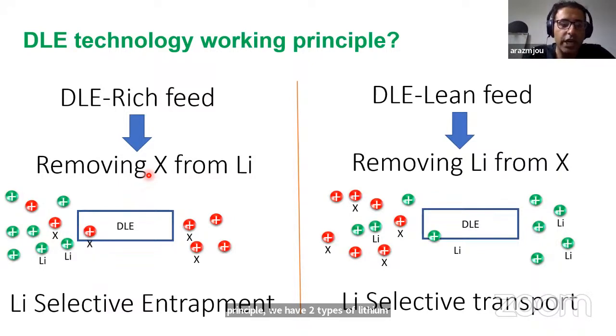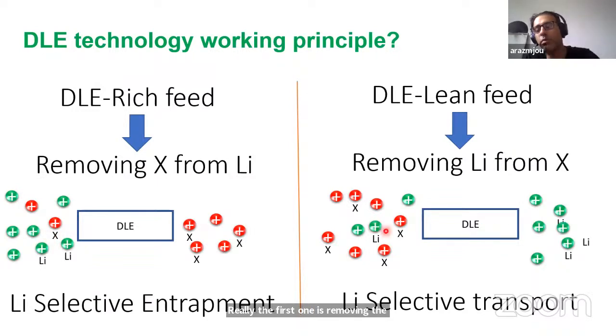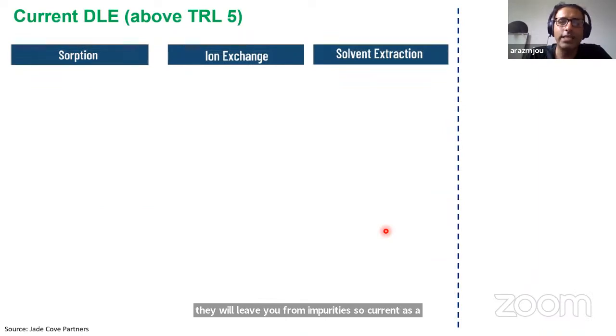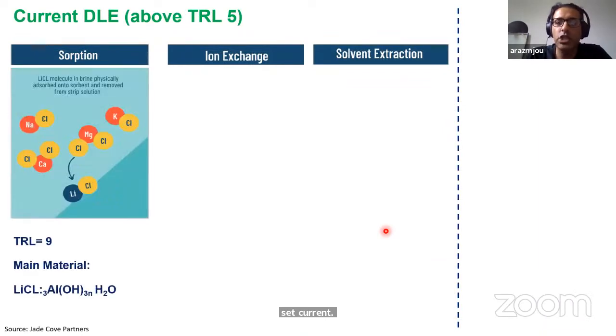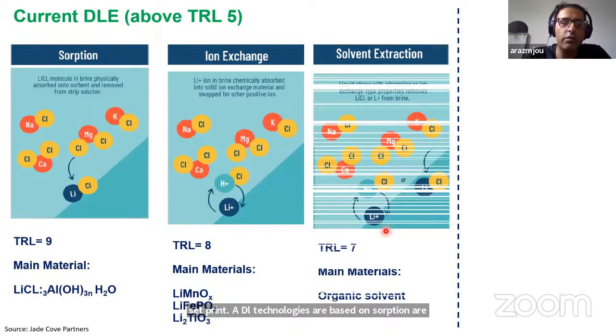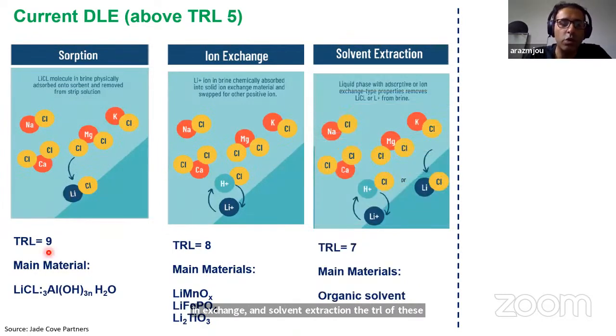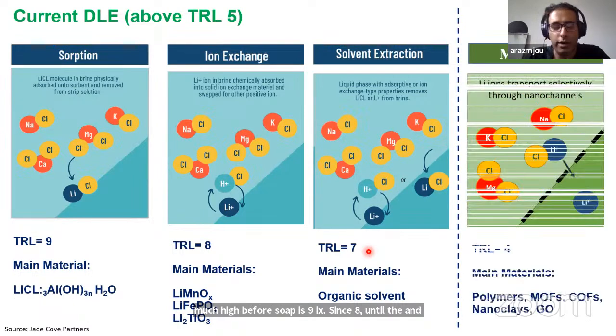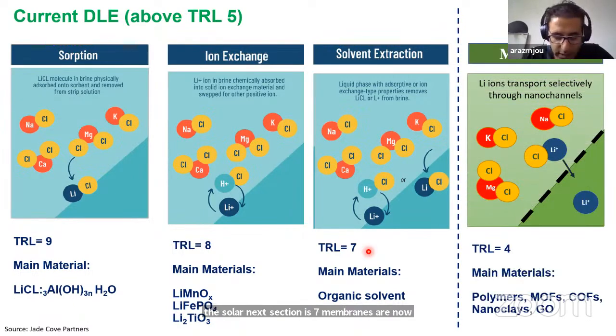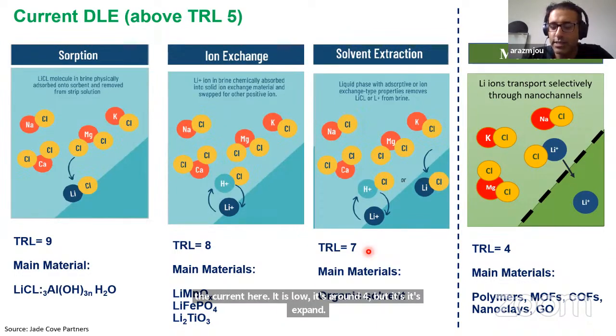In terms of concept and working principle, we have two types of DLE. The first one is removing the impurities from lithium, or removing lithium from impurities. Current DLE technologies are based on sorption, ion exchange, and solvent extraction. The TRL of these technologies is pretty high: for sorption it is 9, ion exchange is 8, and solvent extraction is 7. Membranes are pretty much new. The current TRL is low, around 4, but it's growing so fast in the industry.